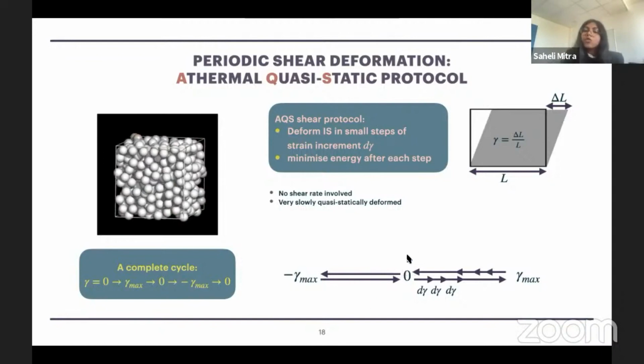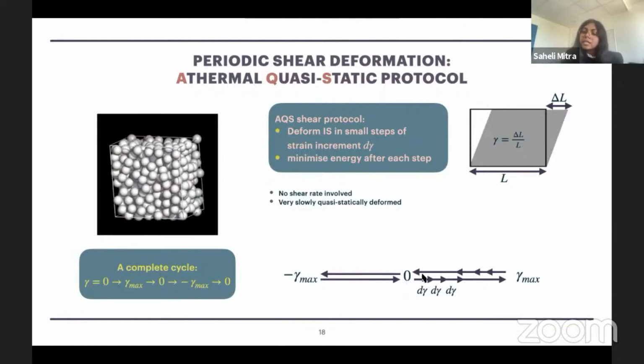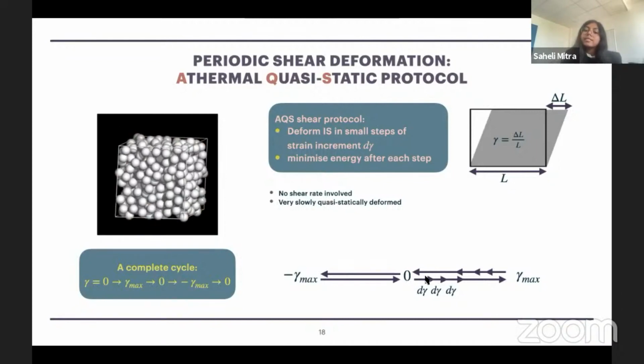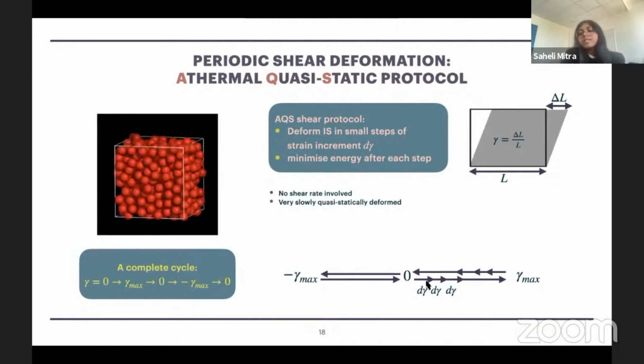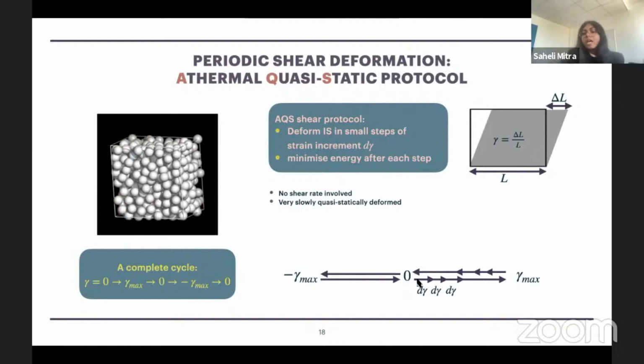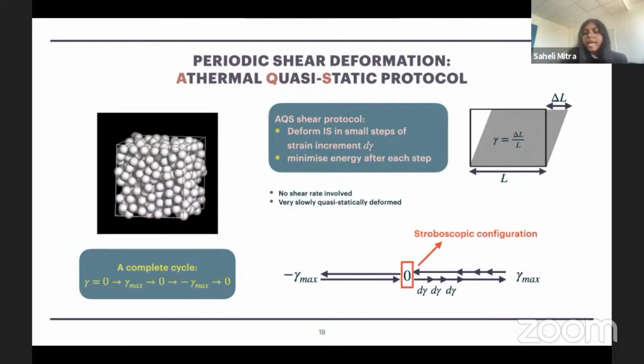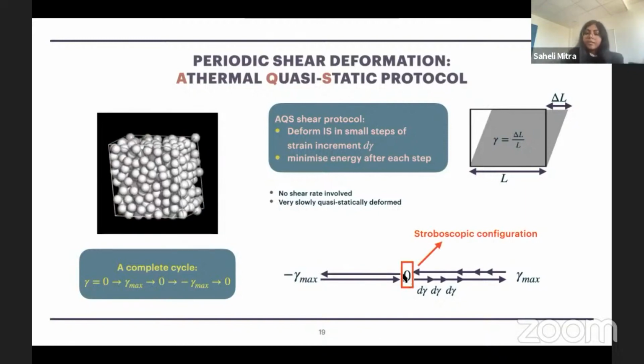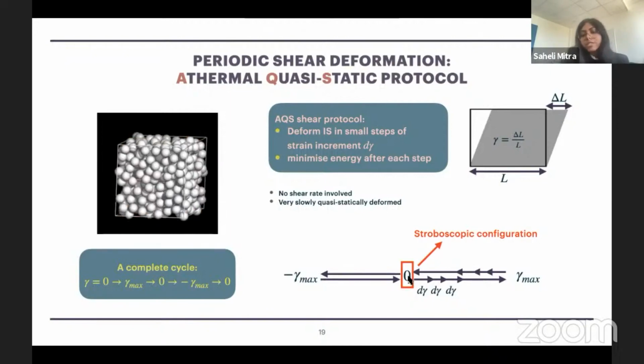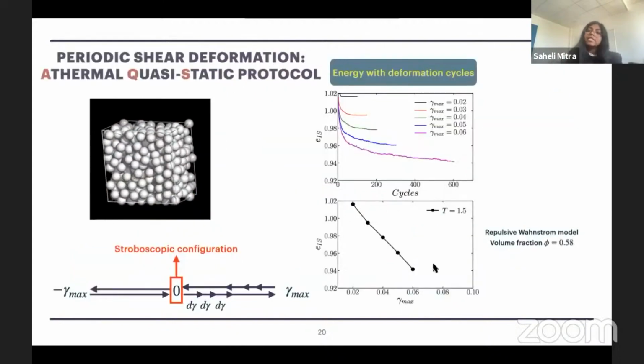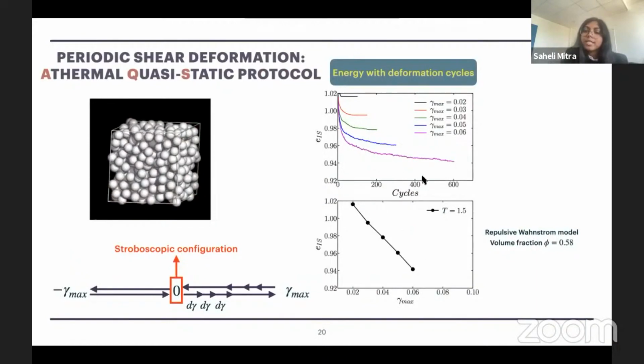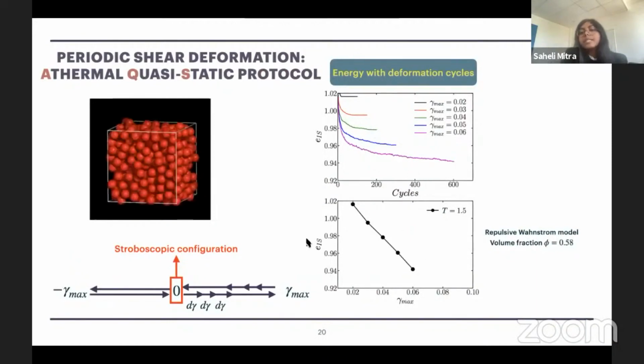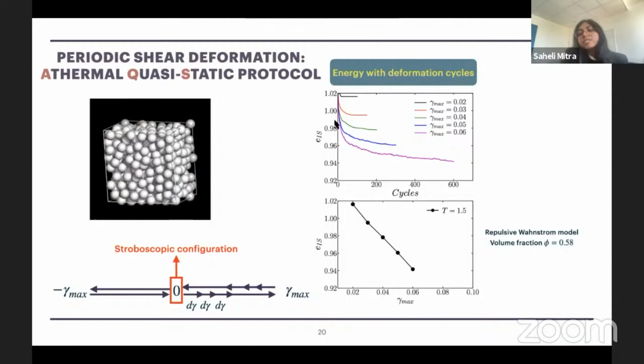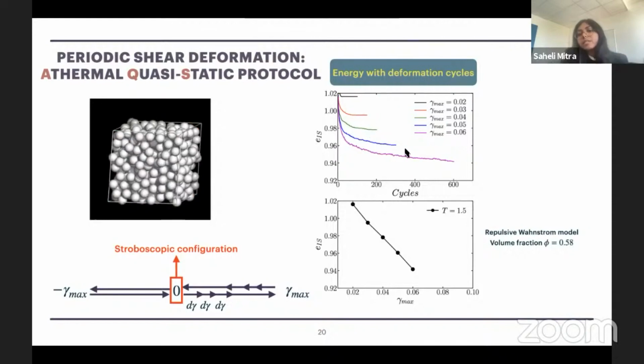So we keep repeating this for many cycles, and after each step of strain increment, we minimize the energy of the system so that it is always sitting in the local energy minimum state. And at the end of the cycles, we actually analyze the stroboscopic configurations where the value of instantaneous strain is 0. So if we plot the energy of the stroboscopic configuration with the deformation cycles, we'll see that depending on the strain amplitude, the system reaches different energy minimum states.